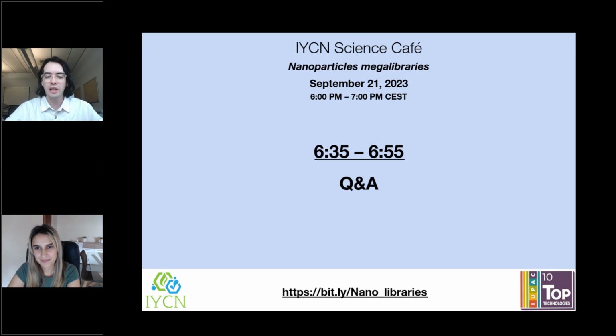There are various methods. The photocatalysis that I discussed is a parallel experiment, so we can do the catalysis of the entire library at the same time. So shining the whole library with light for 30 minutes, so catalysis is happening everywhere. And then do fluorescence microscopy. The microscopy actually also took 30 minutes because it is a centimeter scale chip, and we're taking images that are only maybe a couple hundred microns in width. So it's like 3,000 images that you then stitch together. So that was the longest part. But that's pretty fast, doing everything in just an hour or so of screening.